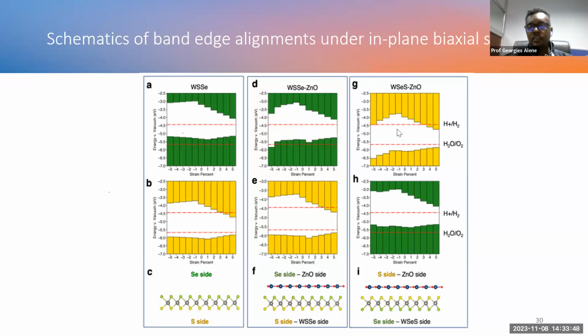I think the trend is more or less similar for both heterostructures, and they have some applicability for overall water splitting. But if we consider one of the cases, that means hydrogen evolution reaction or oxygen evolution reaction, they are actually good depending on the different conditions.